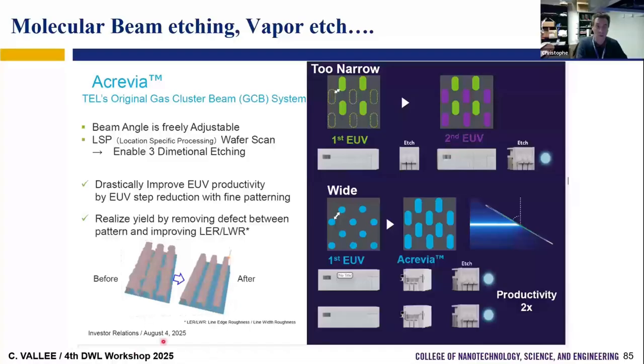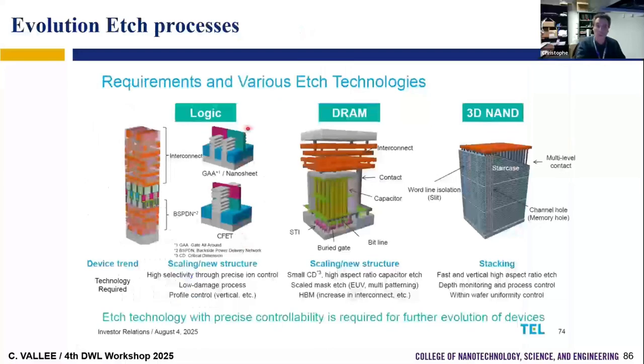So if you look at Tokyo Electron, for example, they have what they call a gas cluster beam system, where they use a gas cluster beam system to try to have better control of the ion energy. So they want to etch not with very big molecules, but a cluster of ions, to try to have less impact regarding the line roughness and roughness due to the ions. Regarding logic, DRAM, and NAND, they have to develop some specific equipment.